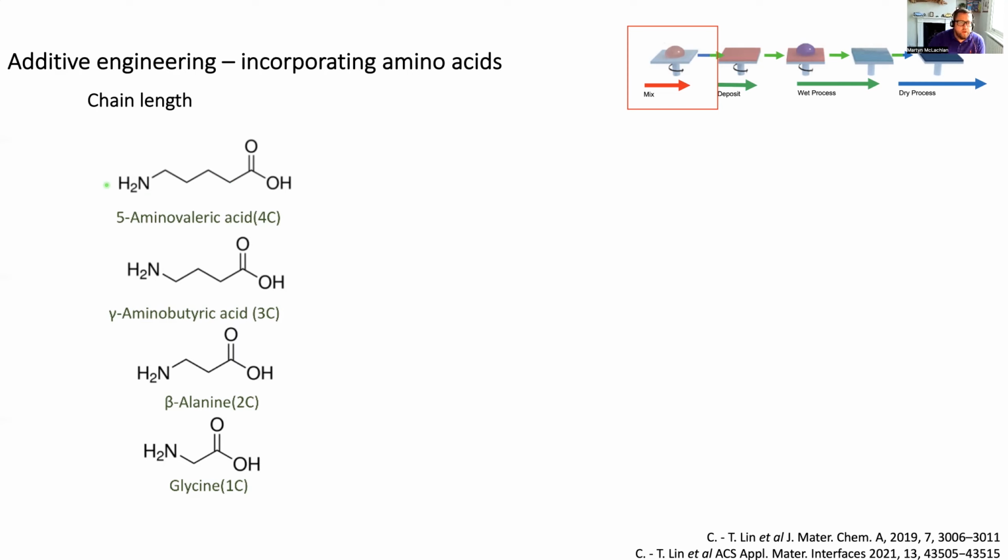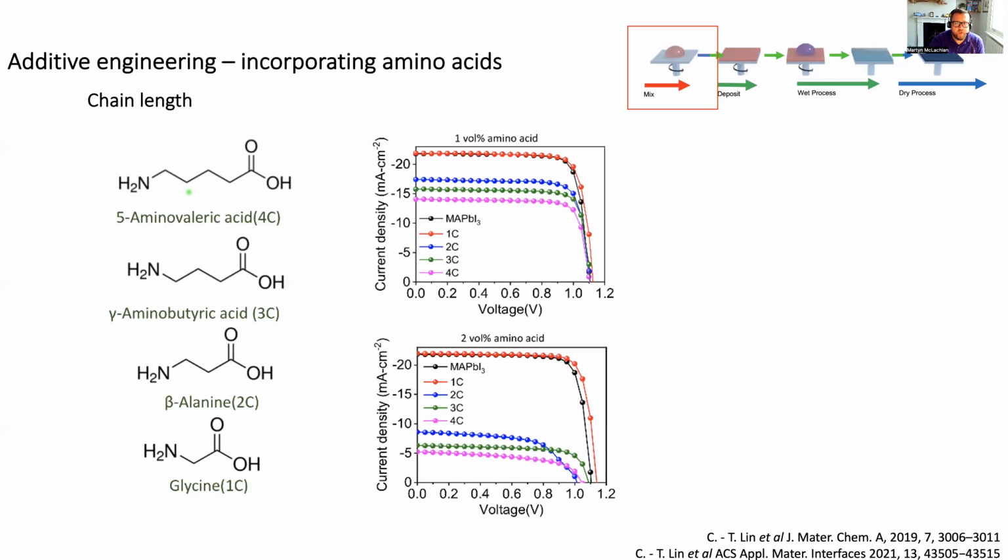Therefore, we're able to have this dual benefit in being able to passivate positive and negatively charged point defects that exist within the structure. So here we wanted to investigate the influence of chain length on these dual aspect materials, with AVA being something that had been reported quite some time ago as a processing additive. The Gratzel group reported this in 2014 in mesoporous cells, and our concern was that the chain length here was perhaps too long, and the passivating effect of the N groups was being negated by the insulating nature of the chain.